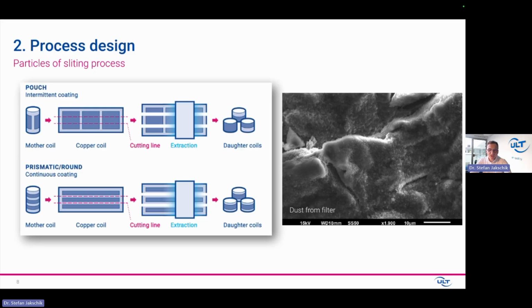You see here a pouch cell and a prismatic cell, and where these cutting processes take place in this kind of production. And when we look at our filters, which run in this kind of production for the slitting process, we see a lot of this dust in the filter. So that means there is indeed a lot of dust available, a lot of particles available, which need to be taken care of. If you have them on the filter, everything is nice. If you don't have them on the filter, something is weird in the production steps.